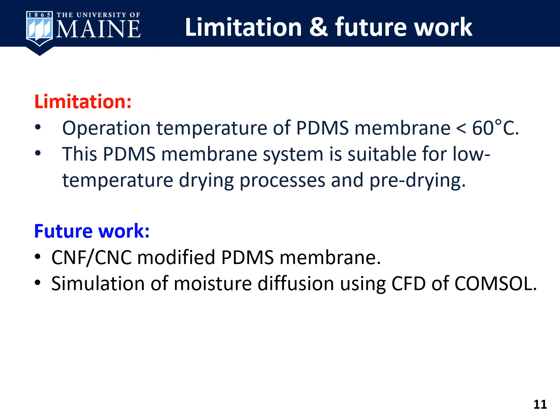The limitation of this PDMS membrane we have identified is that it is recommended to be used in operation temperatures below 60 degrees Celsius. However, we know most wood drying schedules require drying temperatures above this temperature. To solve this issue, we plan to add CNF or CNC into PDMS to improve the moisture diffusion coefficient. We are also developing a computational model to assist in evaluating the moisture diffusion performance of the membrane to be developed.